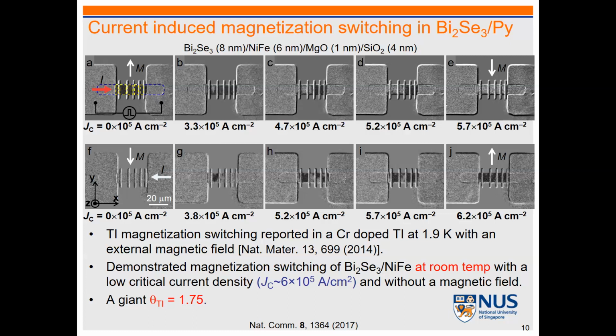And now from this geometry, you can inject the charge current from the right electrode, and you can see eventually we can go back to the black state. So we can go back to the initial state. Depending on the charge current direction, we can switch this nickel iron at room temperature with quite low charge current density. The effective spin Hall angle is 1.75, and many people think, how can it be more than 1? Because it's a conductivity, not total current. So I think this one really attracted people's attention. Topological material can be applied at room temperature for 3D ferromagnet switching.